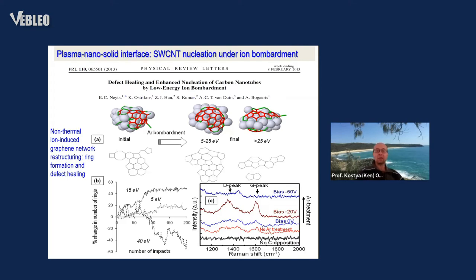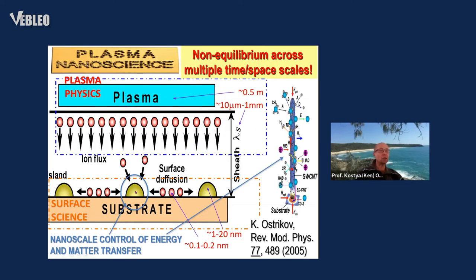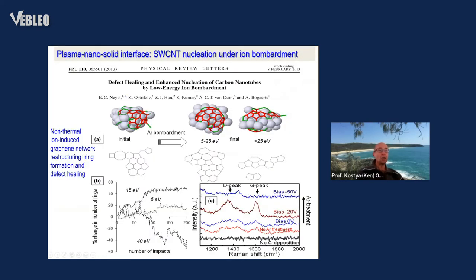Very important thing is that the energy of the ions that are generated by the plasma and are delivered to the surface of this catalyst particle has to be adjusted in a proper way so that it not only causes the nucleation of the carbon nanotube, like the first bent graphene layer, but also does not cause damage to them. And this common perception that plasma exposure, plasma interaction with fragile graphene networks necessarily should induce some damage is not always true.